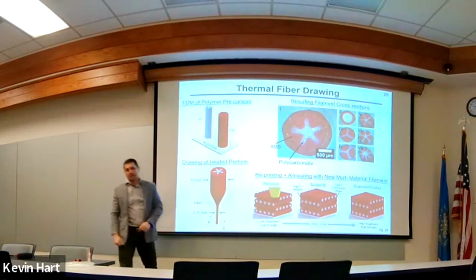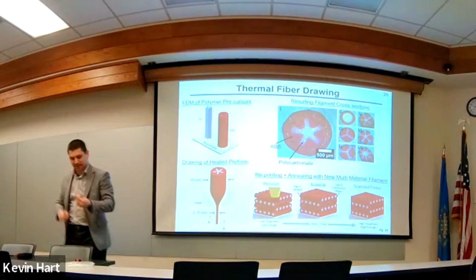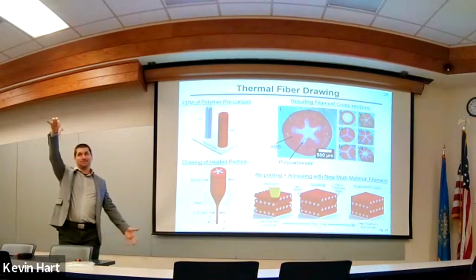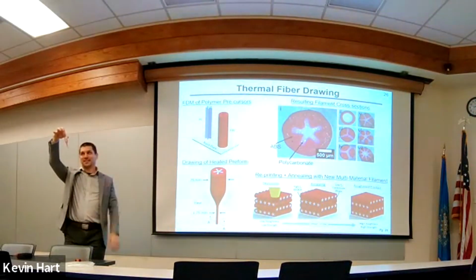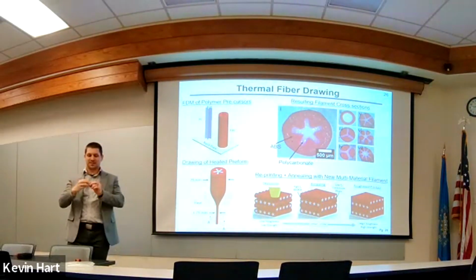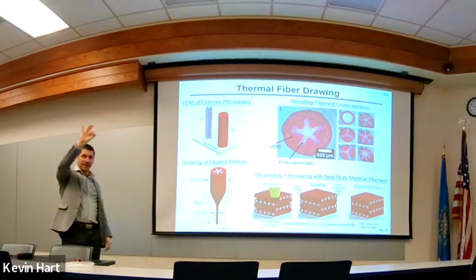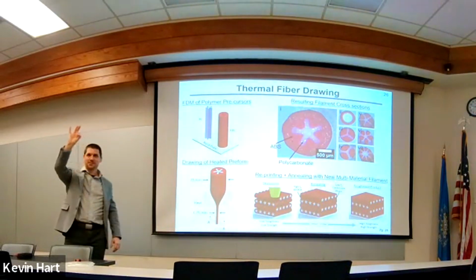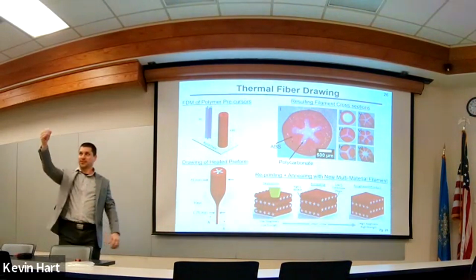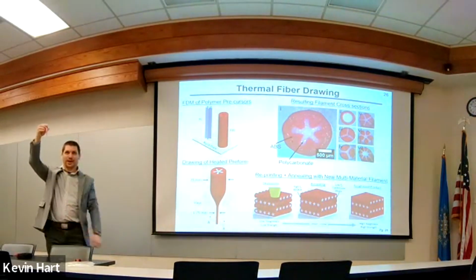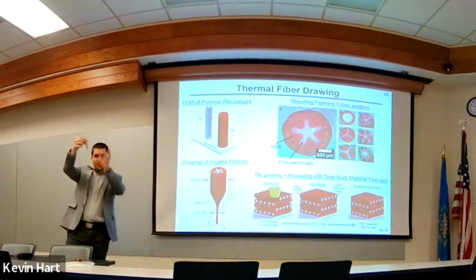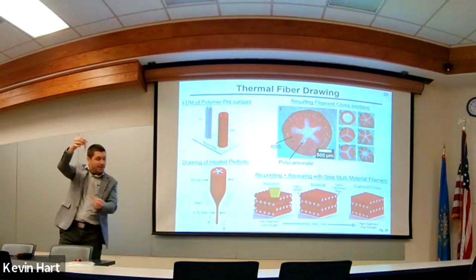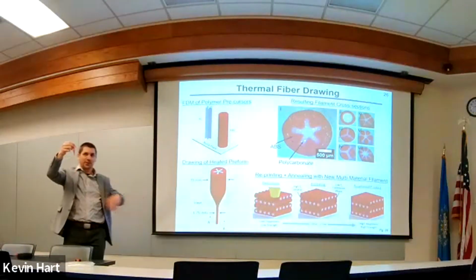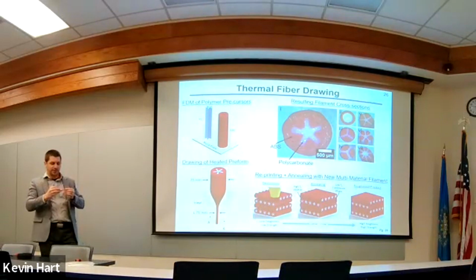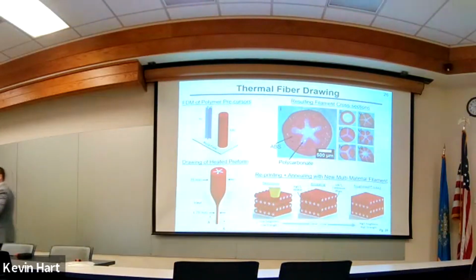It's just drawing down, pulling down this filament to make the cross-sections that we want. So this is what it actually looks like. This is a little preform that I stopped in the middle of the process. You can see that we 3D printed the polycarbonate and the ABS separately, and we jammed them together, and then we put this into our little conical furnace, and we pulled on it in a very controlled way so that we could make a filament diameter with the cross-section that we wanted so that we could feed it into our 3D printer. So I'll pass this around.